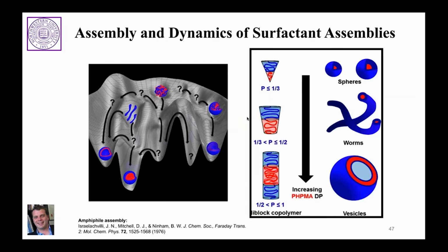And so our approach was really to look at this idea of dynamics from the standpoint of surfactant assemblies. And many of you may be familiar with this. This is the famous kind of picture on the right-hand side here of how surfactants, in this case drawn as maybe a block copolymer, assemble to give you different morphologies. The major driving forces for this are a hydrophobic portion of a molecule, in this case shown in red, and a hydrophilic portion of a molecule, in this case shown in blue, packing together mainly for the reason of excluding water. So this is the so-called hydrophobic effect.